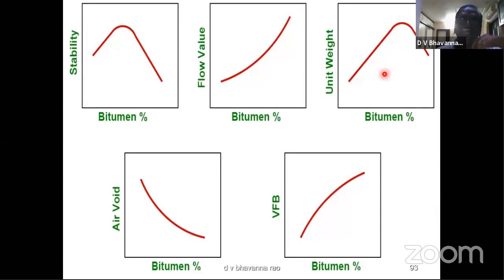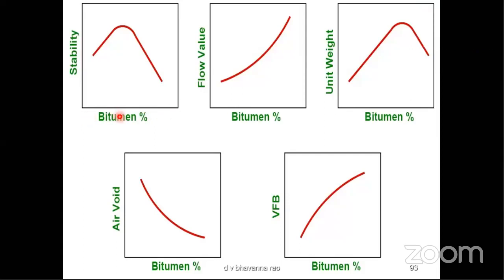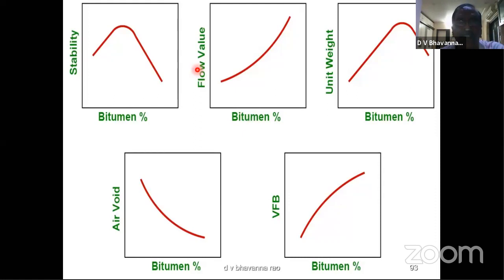Actually, this mix design is to be done for different bituminous contents, keeping in mind the specified bitumen content or minimum specified bitumen content. After this test, we get 5 charts. Bitumen versus stability, bitumen versus flow value. Flow value means the workability. Bitumen versus unit weight. Bitumen versus air voids. Bitumen versus voids filled by bitumen. Considering all the 5 charts, we have to find out the bitumen content at which all the 5 values satisfy the requirement. That bitumen content we have to adopt during execution.